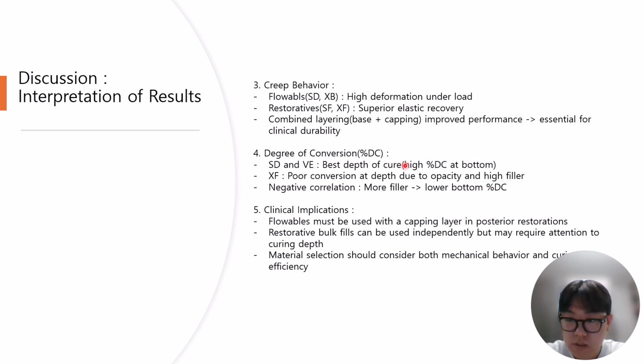Fourth, degree of conversion. SDR and Venus had the best curing depths with high percent DC even at the bottom. Extra Fill had poor conversion at depth due to its opacity and high filler content. There was also a negative correlation: the more filler, the lower the bottom percent DC.